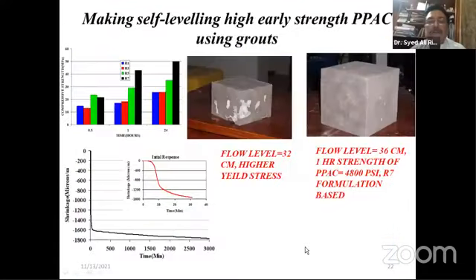You know, I was also interested to make very high early strength cementitious materials. For example, if there is a motorway, or there is some damage to the motorway, then we cannot close the motorway for 28 days. So what we should be doing is to devise some technique on how to restore the traffic as soon as possible. So in this case, I have tried to restore the traffic in 30 minutes,